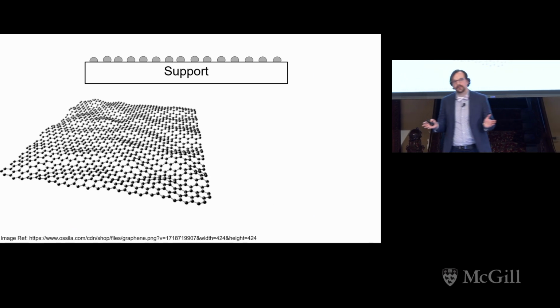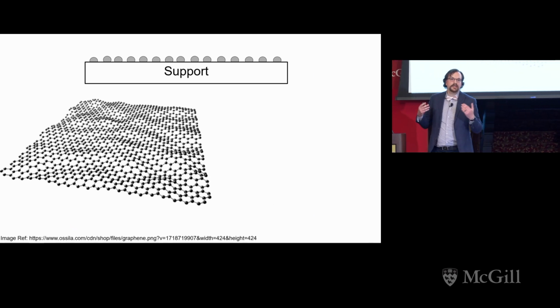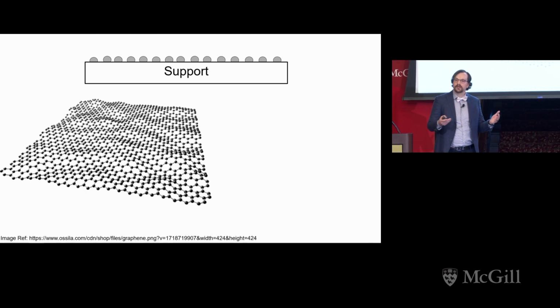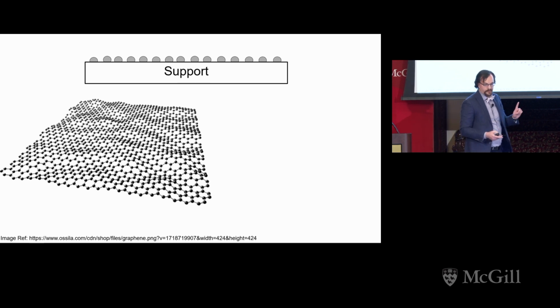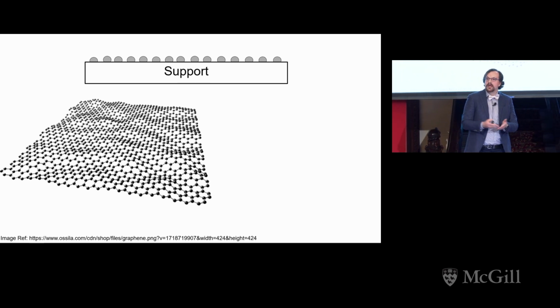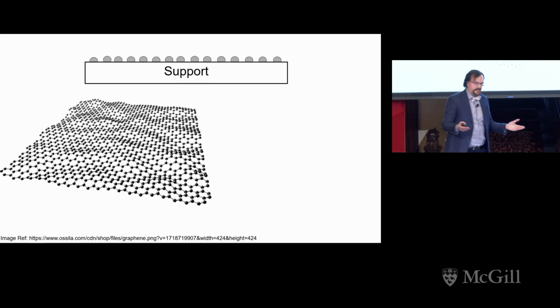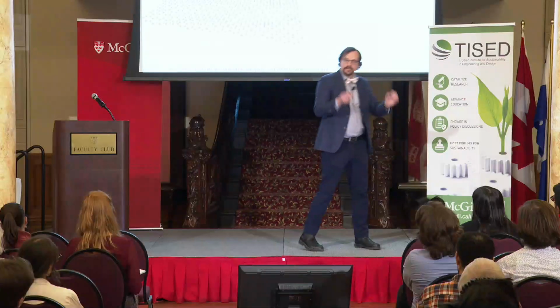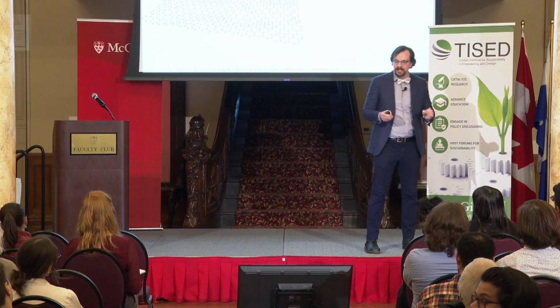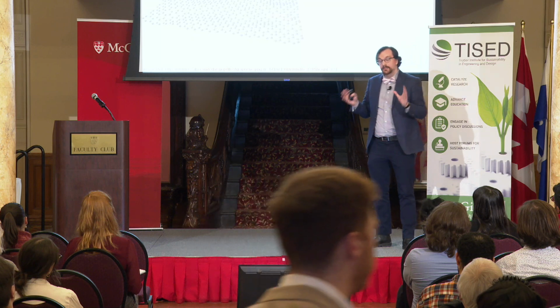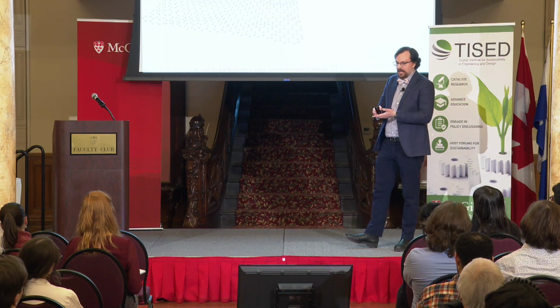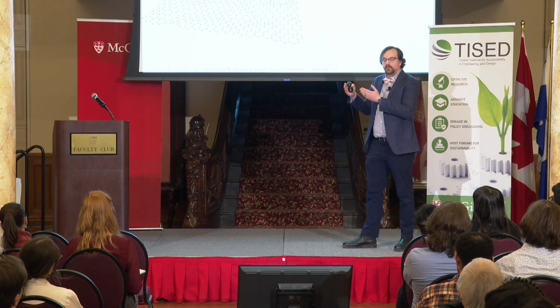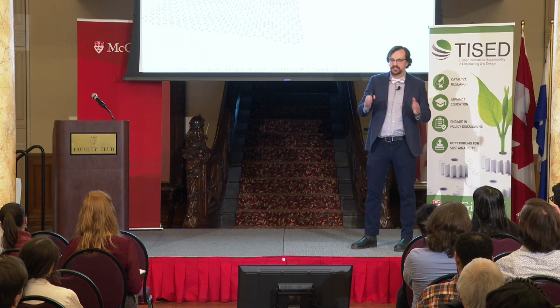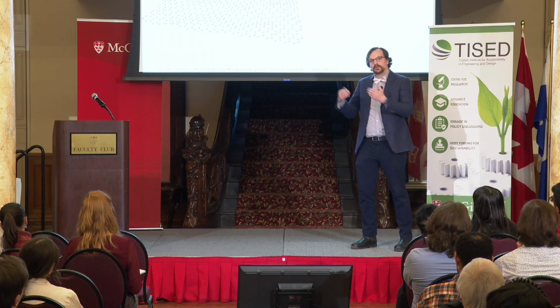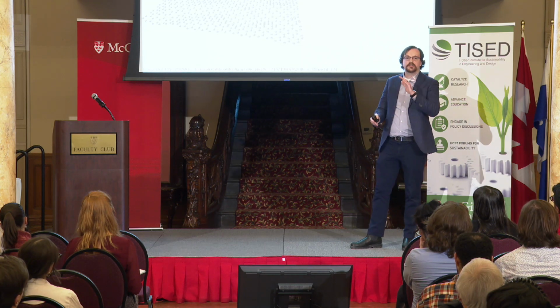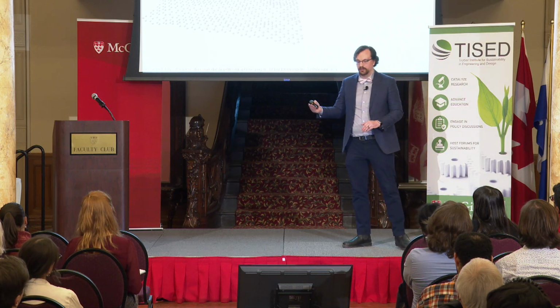There's a couple other ways we can increase the conversion of our catalyst. One of them is we can take the support and increase its surface area. This way, we literally have more spots to put our small nickel particles. The other way is sometimes the support can actually help speed up the reaction with the catalyst. So your reaction speed, hence your conversion, is actually faster with a support and catalyst than the catalyst alone.